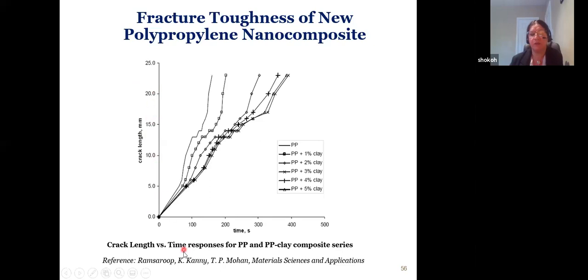Here I have an article from Material Science and Application that shows you. When I have just polypropylene itself, with nothing inside as reinforcement, we make a notch, a kind of crack in the specimen, and then give it time. After a while, you see the crack propagation happening, the length increases to 25, and then you get fracture.